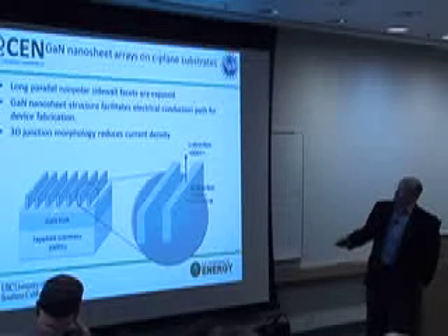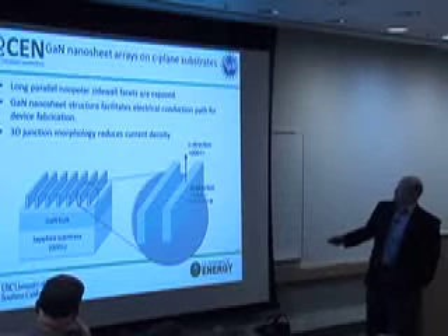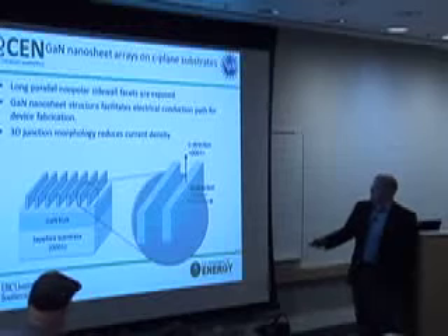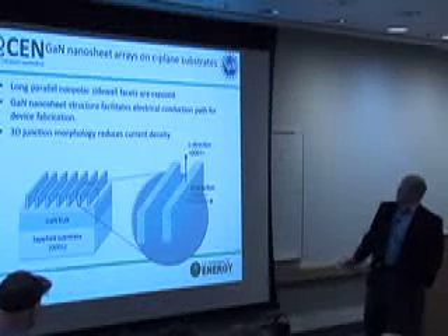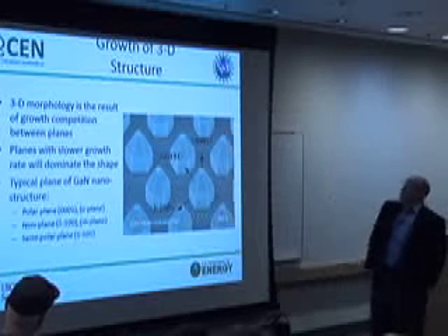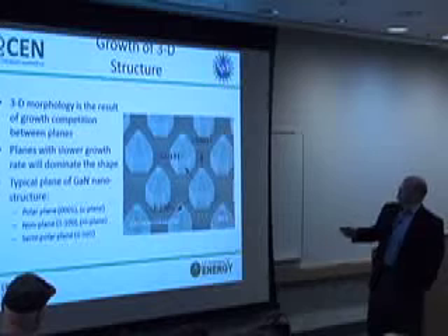We've also looked at structures where instead of nanorods, we've structured the pattern so that we grow nanosheets of gallium nitride with M-plane surfaces, and we can grow quantum wells on these surfaces as well. So, growth of these kinds of structures requires the control of the kinetics of growth.